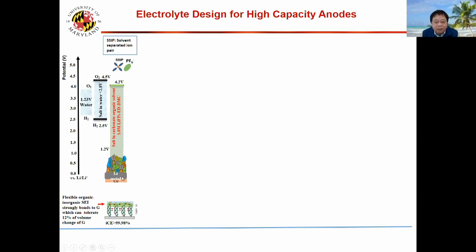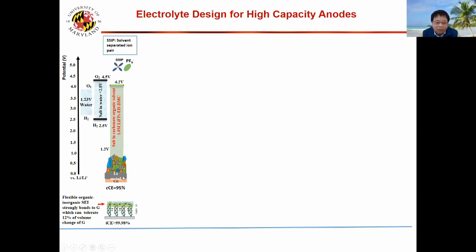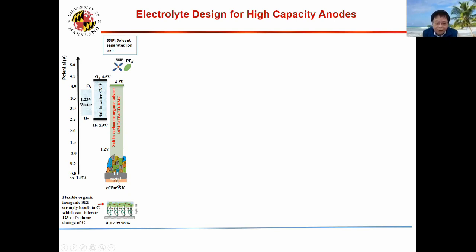Efficiency can reach 99.98%, so we can ensure 1,000 cycles. But if we use lithium metal with the same electrolytes, we find out the efficiency is only 95%. Why is it lower? We believe the reason is the SEI is also strongly bonded with lithium because they have a polymer. When bonded with lithium, the lithium volume change is not 12% — it's effectively infinite. When the volume changes a lot, the SEI strongly bonded with lithium metal also has similar volume change because the bond is so strong. No material can withstand such huge volume change. They will crack, leading to lower efficiency.